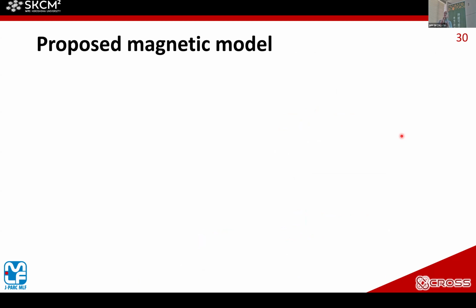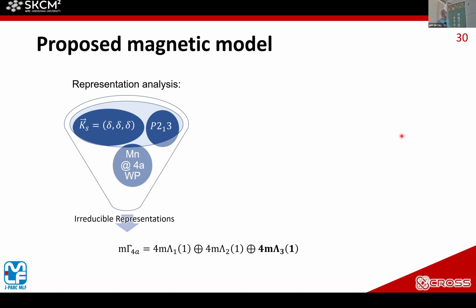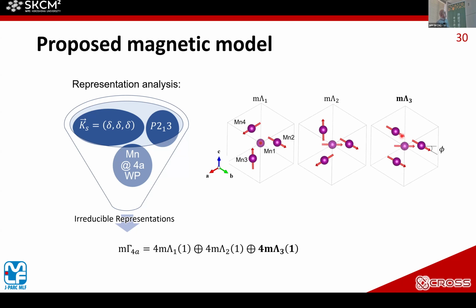Then, to extract what kind of magnetic structure exists in the conical phase and the skyrmion lattice phase, we need a model to extract the magnetic structure from the internal field. According to the irreducible representations, we have several conditions: the propagation vector and the space group, and we know the manganese position at the 4a position. So using these conditions, we can estimate the magnetic structure of the manganese site, like these three magnetic structures.